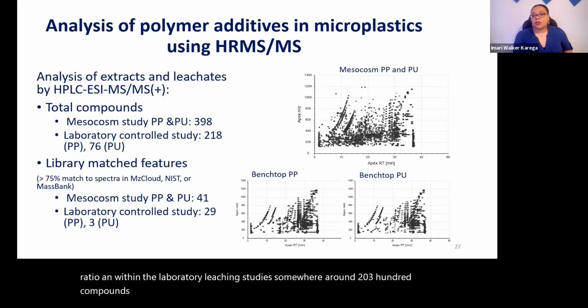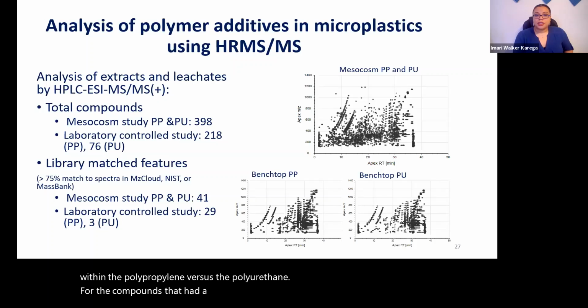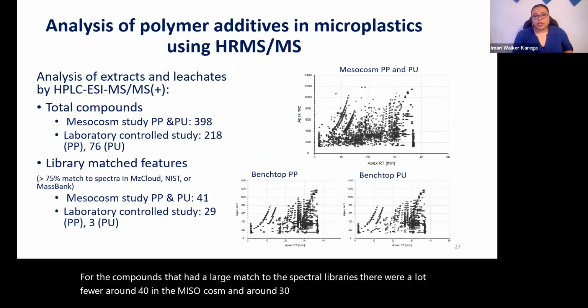There's quite a big difference between those found within the polypropylene versus the polyurethane samples. For the compounds that had a large match to the spectral libraries, there were a lot fewer, around 40 in the mesocosm and around 32 in the laboratory controlled studies.